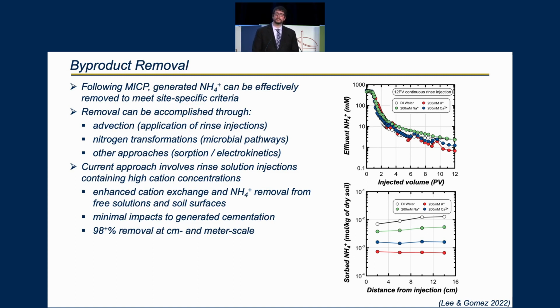As shown, we can track changes in aqueous ammonium exiting the column versus injected pore volume. And we can also track changes in sorbed ammonium concentrations as a function of soil column distance. When comparing different solutions, such as the plot shown here, it's clear that supplied rinse solution cations can enhance cation exchange of sorbed ammonium concentrations and get effective removal from both pore fluids and soil phases. The net result at the end of this is that we're able to remove approximately 98% or more of the ammonium that's generated at meter scale as well, with minimal impacts to the cementation overall.